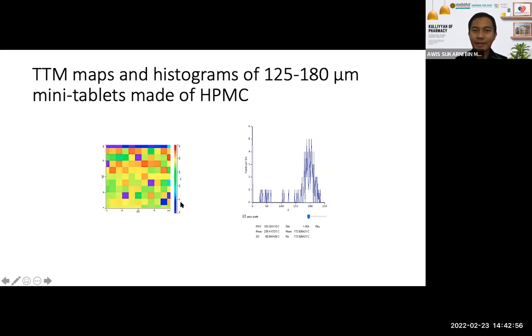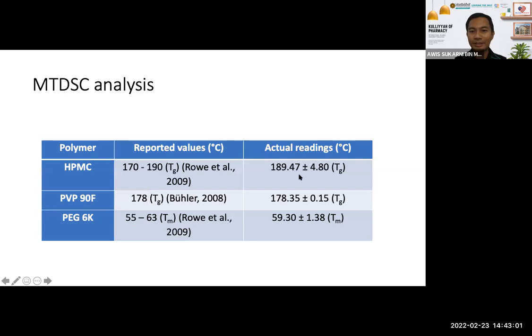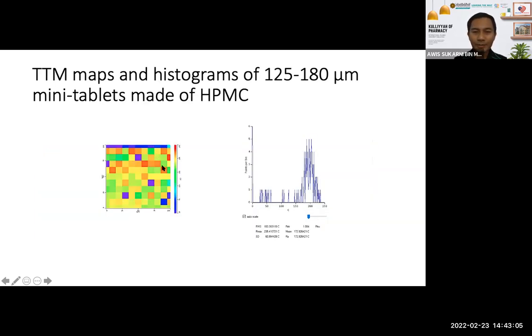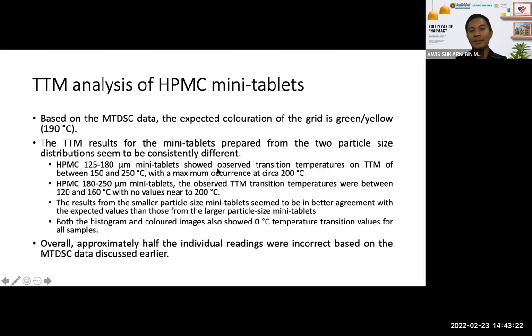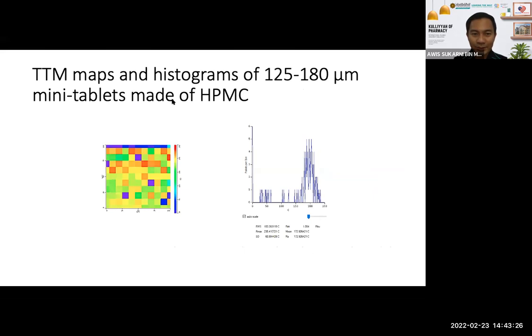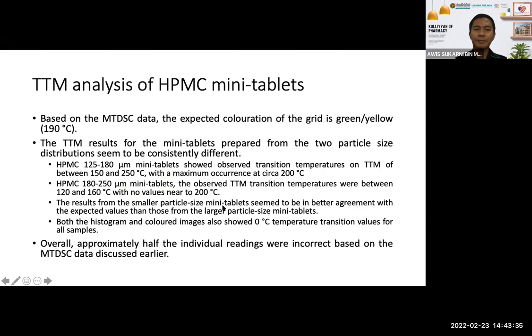And for the HPMC, as mentioned here, the actual reading should be around 190 degrees. But here you can see the result: there are 6 points that showed a 0 degree result, and then there are several here and here, so it's scattered. Based on the MTDSC data, we expect the color of the grid to be green or yellow, because green and yellow should be around this region, so around 190 degrees. So it should be green and yellow only. But from the map, you can see there are a lot of different colors. This means it shows different temperatures in the range from 25 to 250 degrees. And for the smaller particle size of the tablet, it shows temperatures between 150 and 250, whereas the maximum occurrence is around 200 degrees Celsius.